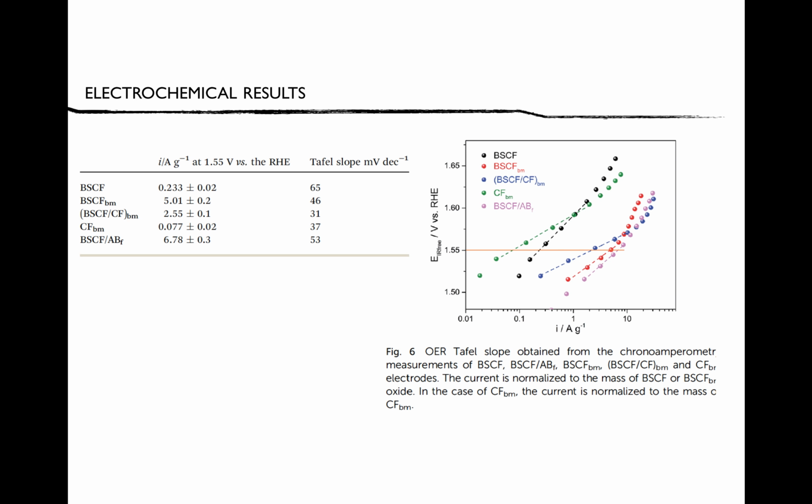I'm not going to go through all of them, but cyclic voltammetry covered a voltage of 1 to 1.7 volts, and the one we see in figure 6 has resulted in 1.55 volts. This one is a logarithmic scale, and there's almost a 20 times increase in the milled particles compared to the unmilled particles.